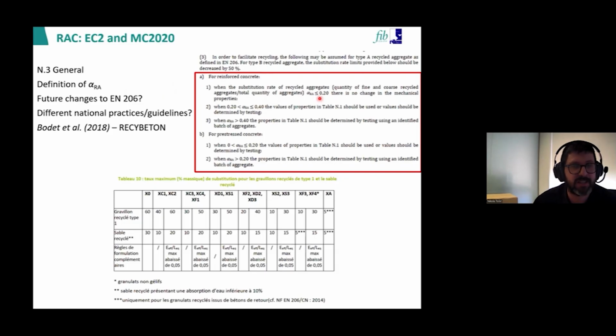So there are some limits that say if you use up to 20% of recycled aggregate, but total that can be 20 and 20, fine and coarse, or if it's only coarse, depending on the ratio between fine and coarse, you can end up using 35–40% of coarse aggregate and still be within the limit. There is no change in the mechanical properties. This is what all the literature shows. If you go up to 40, then you use what is in the table. I mean, you change the properties based on the equations. If you go above 40, you have to test. Yeah? And this is for reinforced concrete.